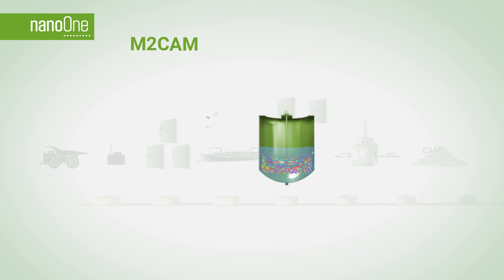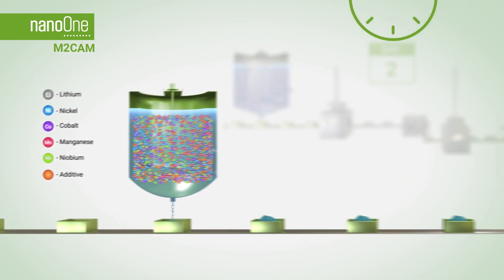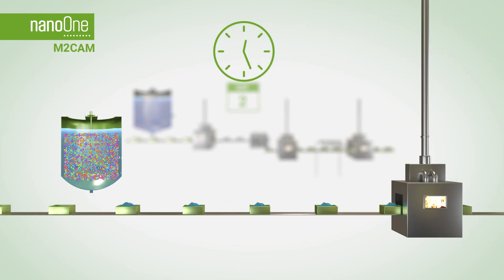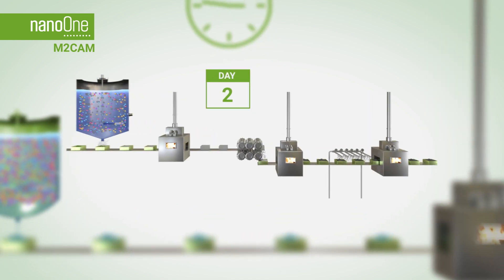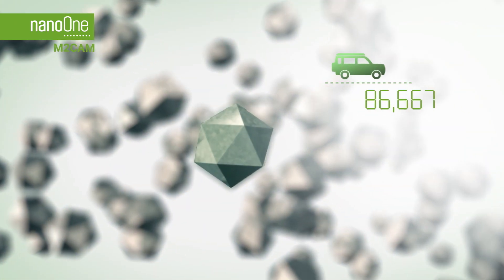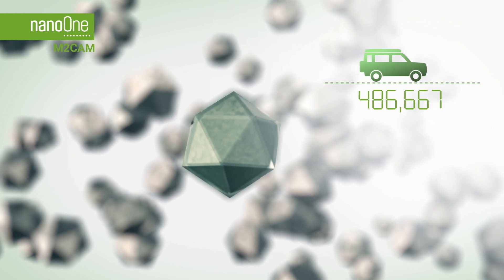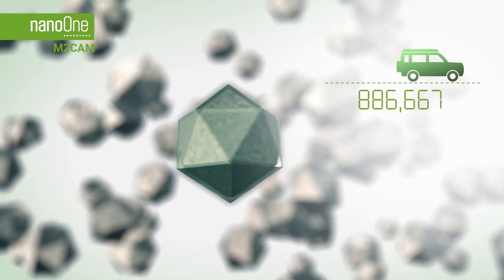We use 20 times less water to produce a composite powder that reacts in the furnace in a matter of hours instead of days. We form coated single crystal cathode powders with no extra steps for improved durability in batteries.